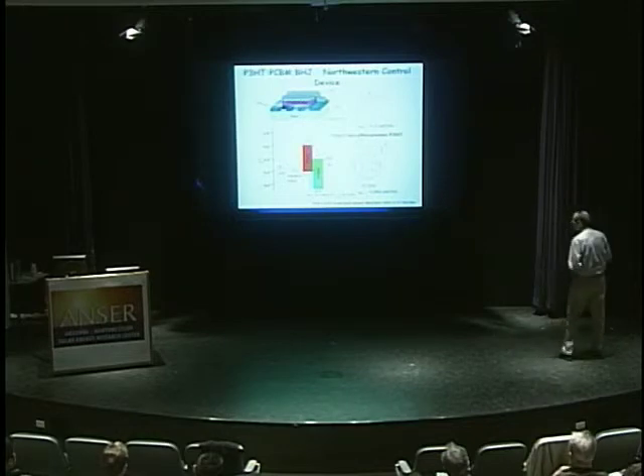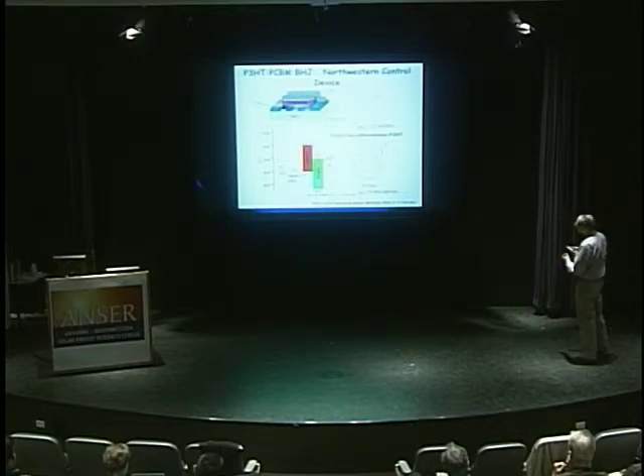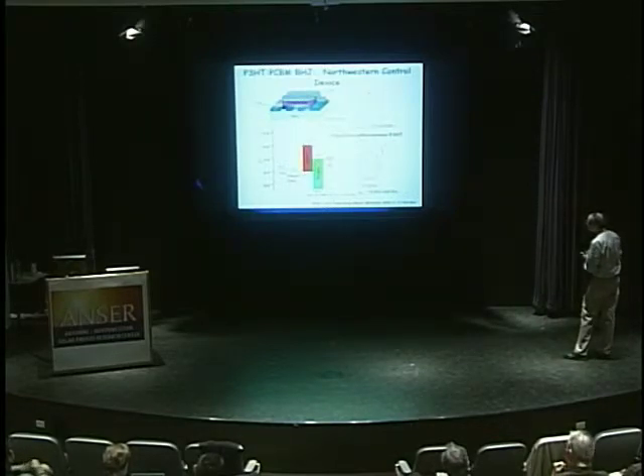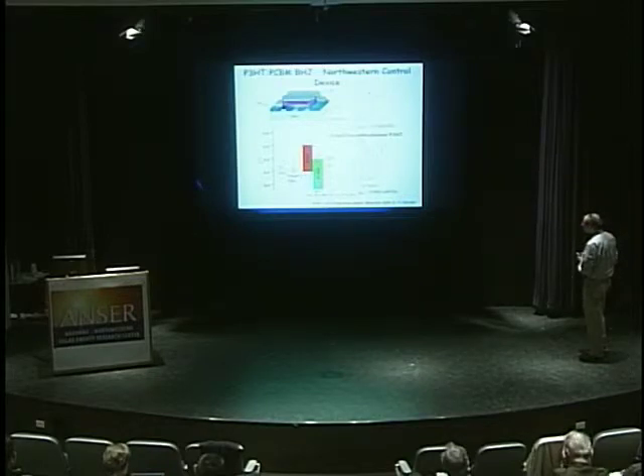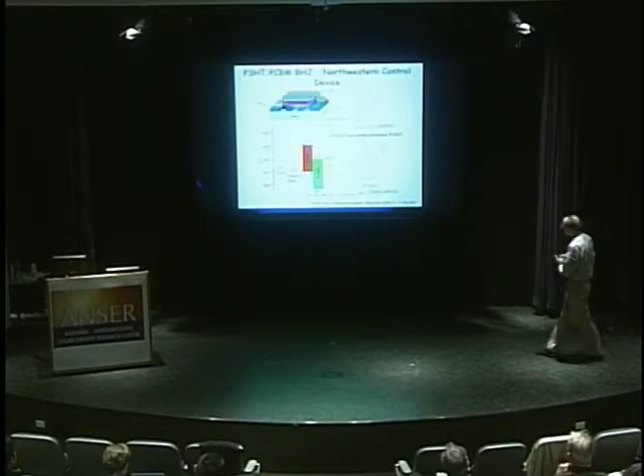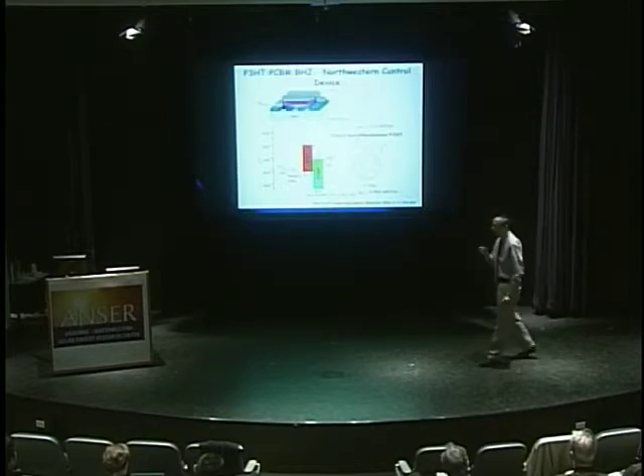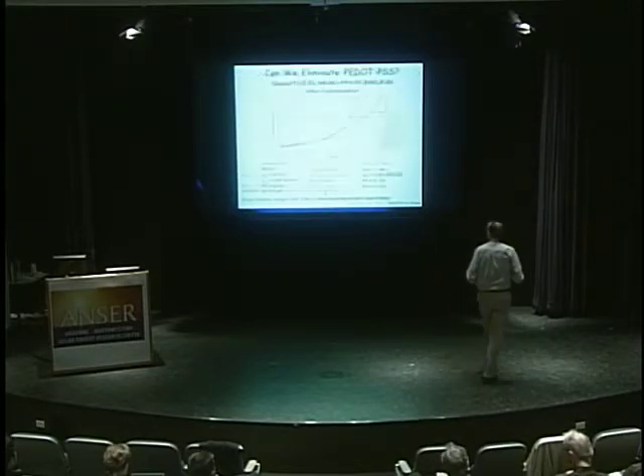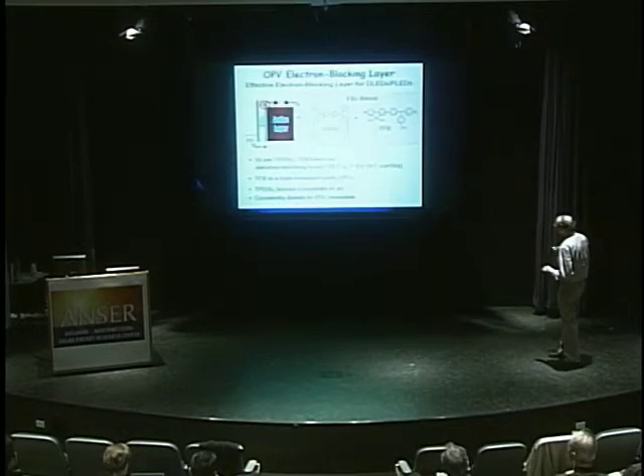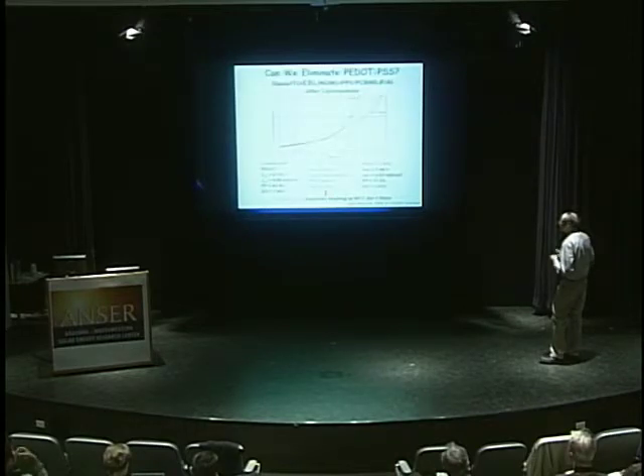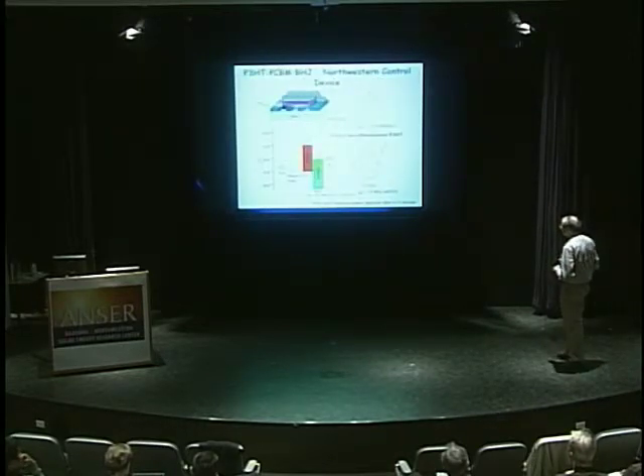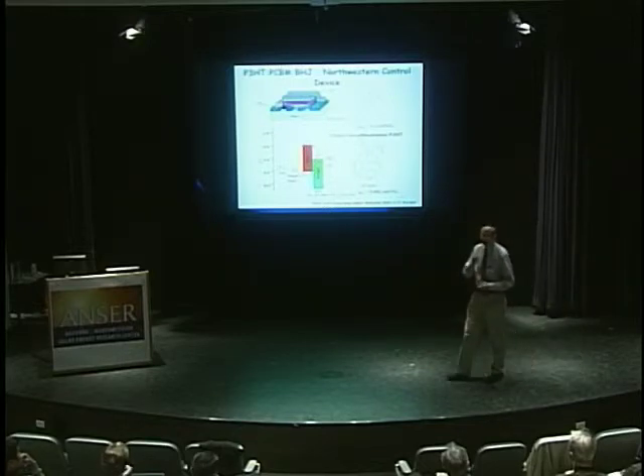So then you say, well, okay, so the PPV systems are interesting, but let's get to something which has a higher power conversion efficiency. So now we're going to switch and look at this polythiophene C60 material, and this is well developed in the literature. These are what the energy levels look like. And it turns out that this particular material is not well suited for this particular hole injection layer. We've now got one that it is, but this one, it doesn't have a good matchup of the energy levels, and we can show that in lots of measurements. So we thought, let's really try something out of the box.